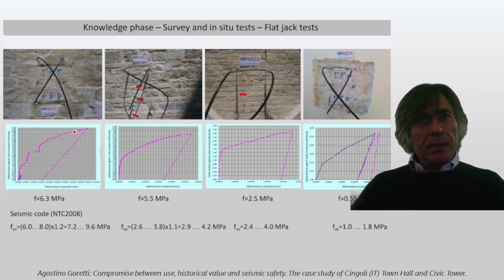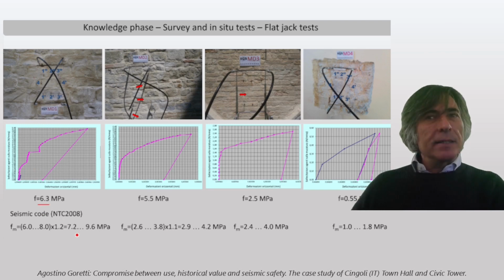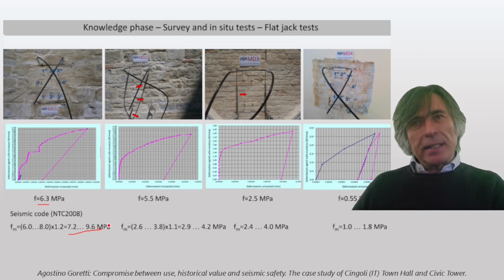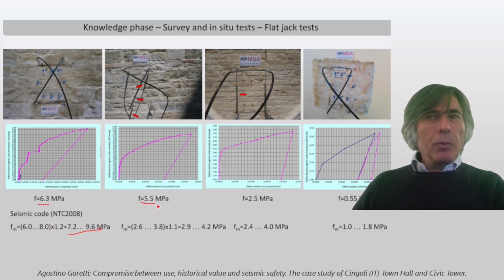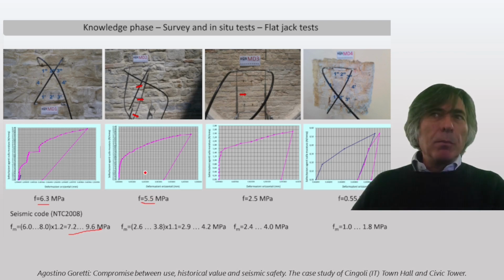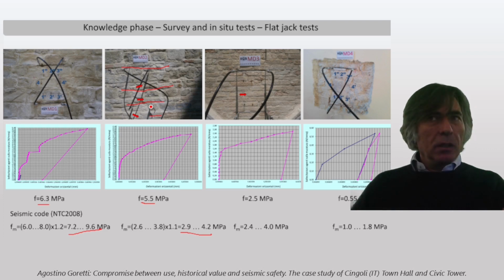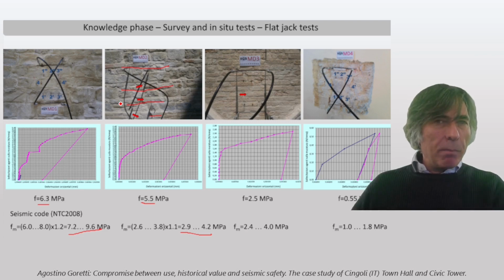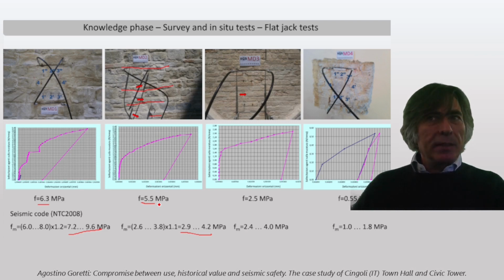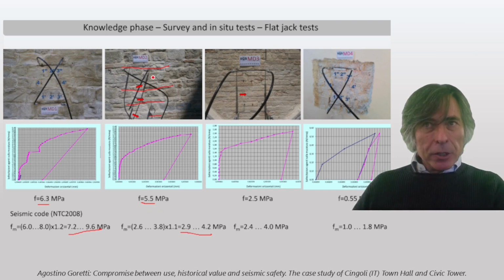So what we found is that in the best quality masonry we get 6.3 resistance, which is a little bit lower than the range suggested by the code, considering several factors. I'll not go through this detail. Important is to understand the value with respect to the range. In this a little bit more irregular layout, we found that the resistance is even more than what is considered in the code, and this is probably due to the fact that the distance of these courses is quite small. Usually there are 70-80 centimeters, even 1 meter distance. Here we are talking about maybe 20 centimeters, so it regularized the masonry very much.